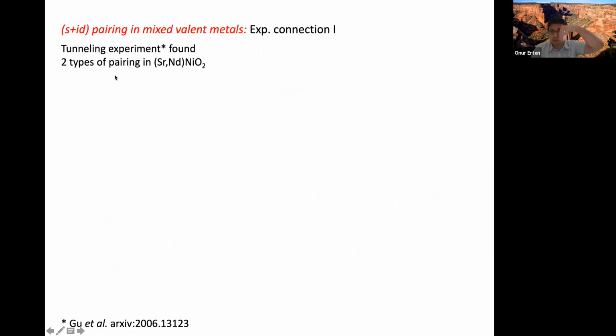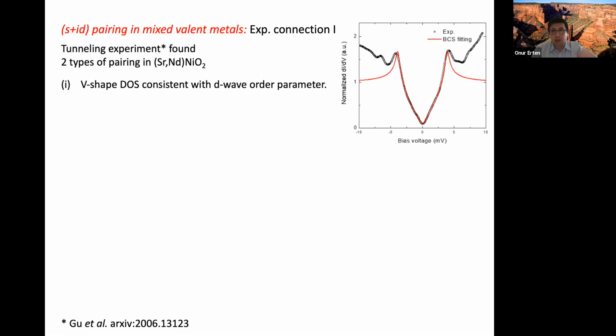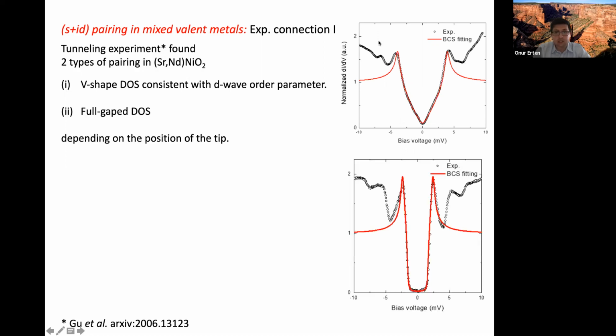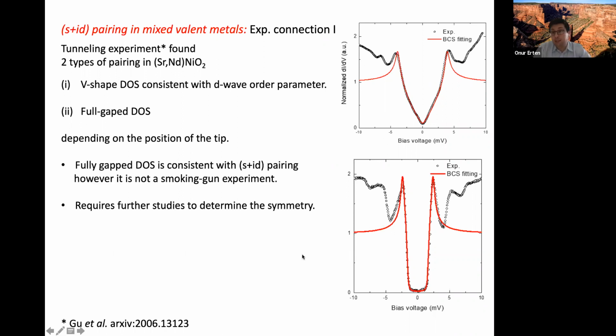You come with a tip and you look at the density of states. Depending on where you put the tip, they find either a V-shaped density of states, which is related with D-wave superconductivity, or in some cases, they find fully gapped superconductivity. This is very strange because if you have a uniform phase, you would expect the same type of density of states everywhere. But having two types of superconducting orders coexisting is quite unusual. And this does not prove that it is s+id, but it is in agreement with it.